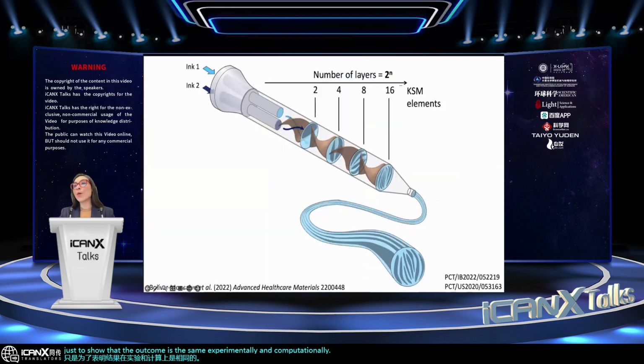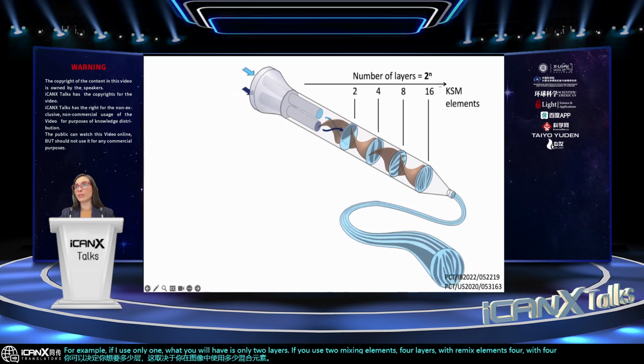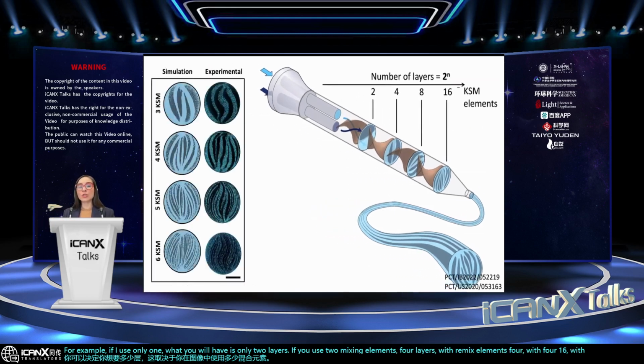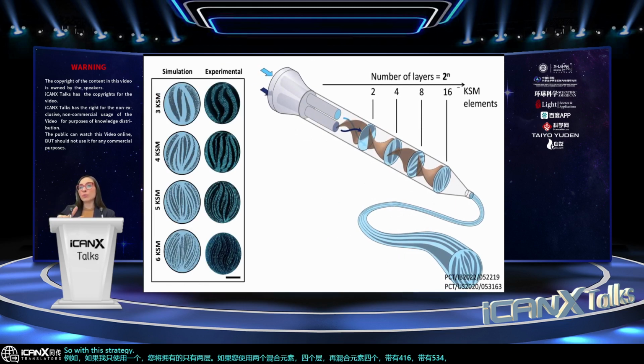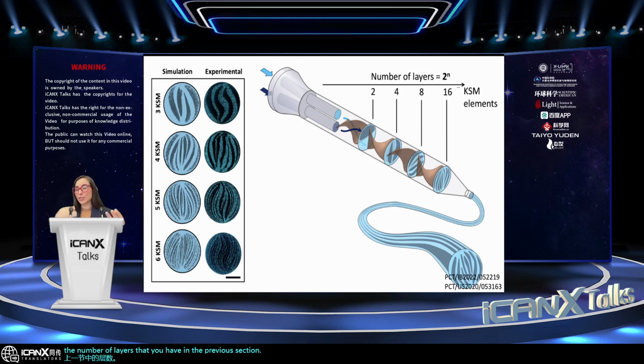And you can decide how many layers you want, depending on how many mixing elements you use in the printhead. For example, if I use only one, you will have only 2 layers. If you use 2 mixing elements, 4 layers; with 3 mixing elements, 8; with 4, 16; with 5, 32; and so on and so forth. So with this strategy, you can multiply by 2 the number of layers that you have in the previous section in a very easy way, just by adding 1 more mixing element.